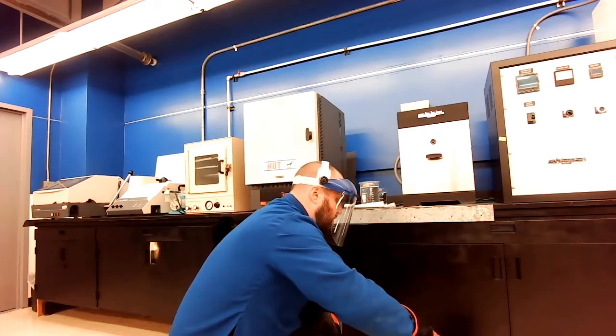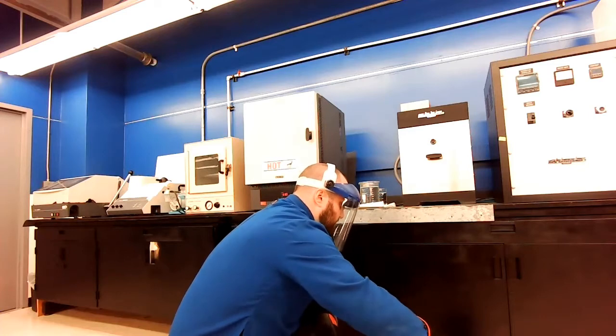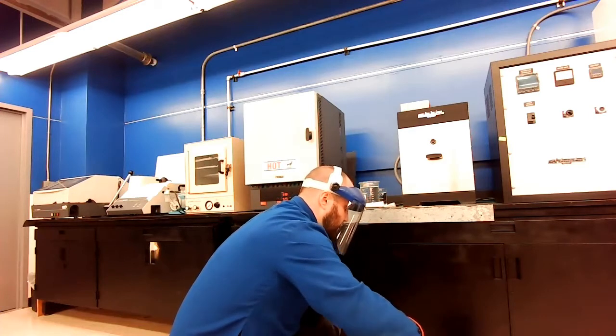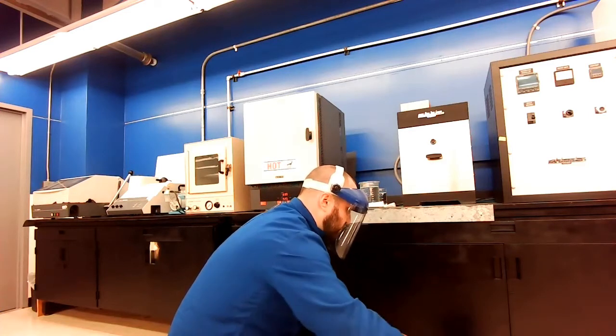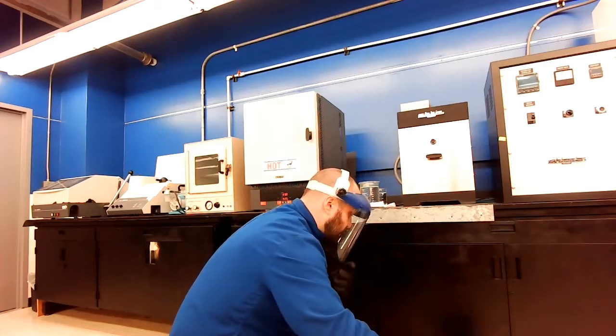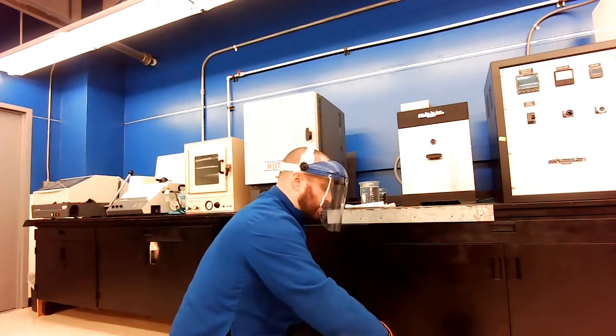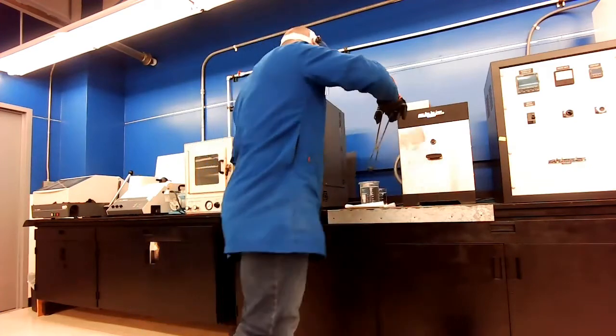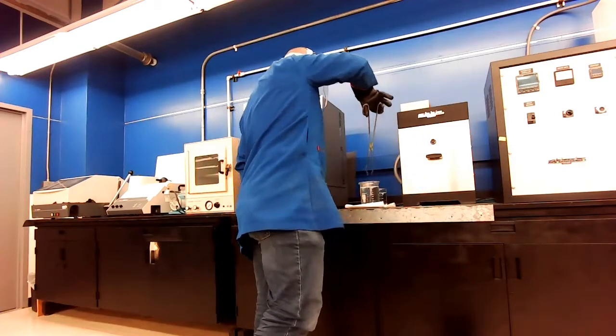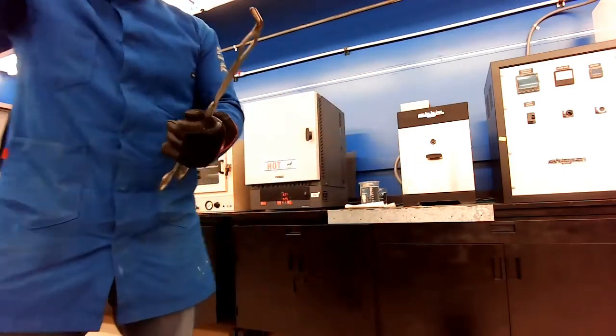After a minute or two, I see that no more bubbles are coming off. Again, that means I'm below 100 degrees C. I can take and put this sample into my regular water as well.